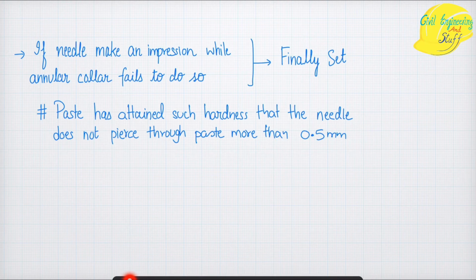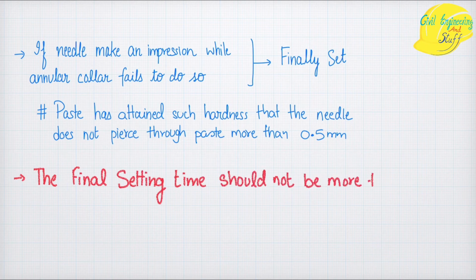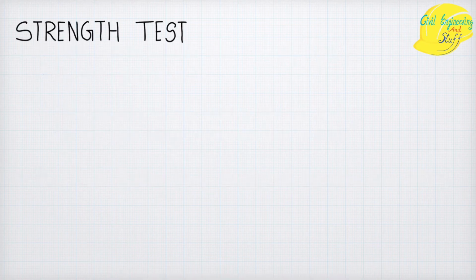Now the paste has to obtain such hardness that the needle does not pierce through the paste more than 0.5 mm. The maximum penetration that is permissible is 0.5 mm. Now the final setting time should not be more than 10 hours.